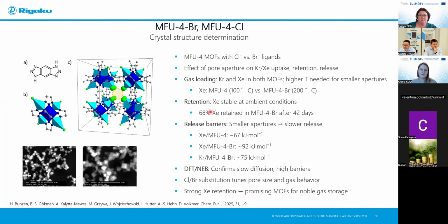So the next example of MOFs, MFU-4 bromide. In this case, we combine two different techniques, powder diffraction and electron diffraction. In this research, the goal was to investigate how the pore aperture influences the krypton-xenon uptake, retention, and release. It was confirmed that in case of the bromide phase, xenon was stable at ambient conditions, and 68% of xenon was retained in MFU-4 bromide after 42 days.